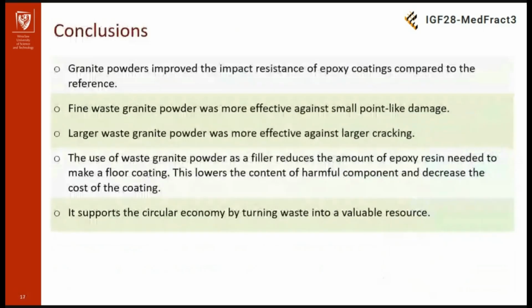Finishing with the conclusions, granite powders improve the impact resistance of epoxy coatings compared to the reference samples. Fine waste granite powder was more effective against small point-like damage. The larger powder was more effective against larger cracking. The use of waste granite powders as a filler reduced the amount of epoxy resin needed to make the floor coating. This lowered the content of harmful components and decreased the cost of the coating. It supports the circular economy by turning waste into a valuable resource.